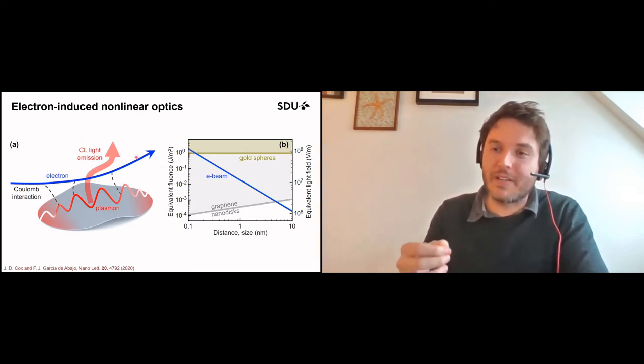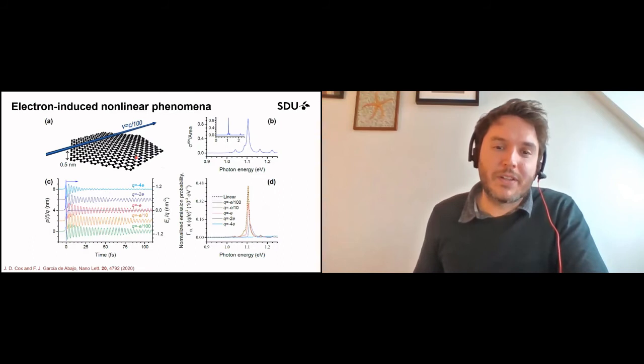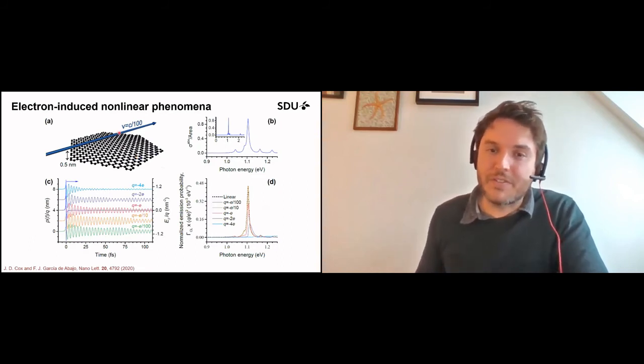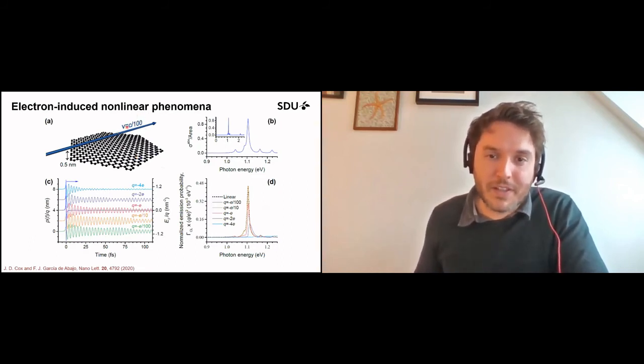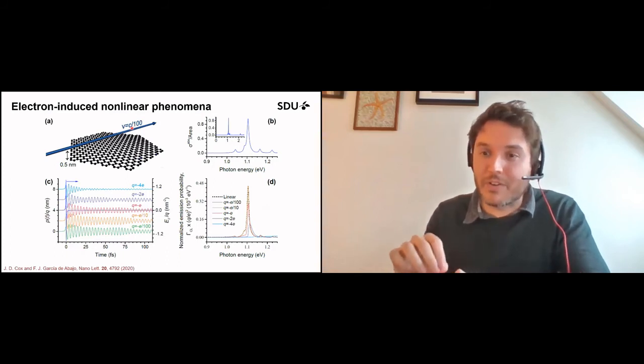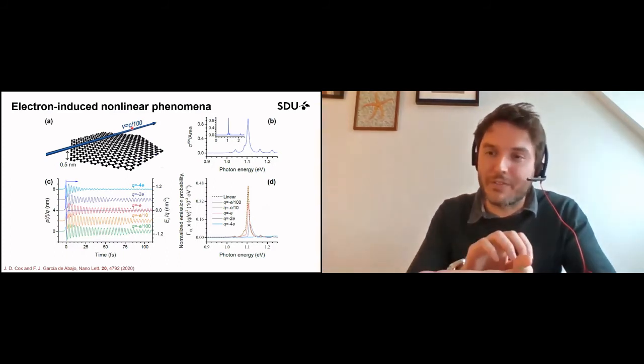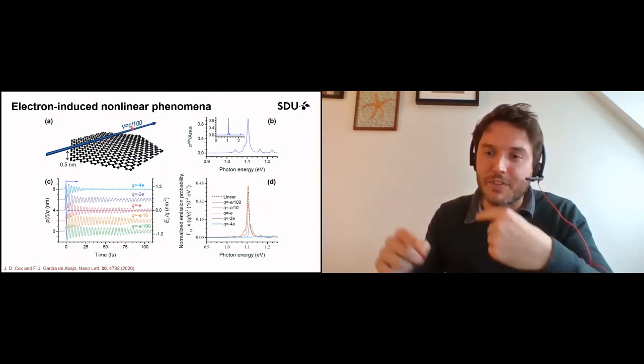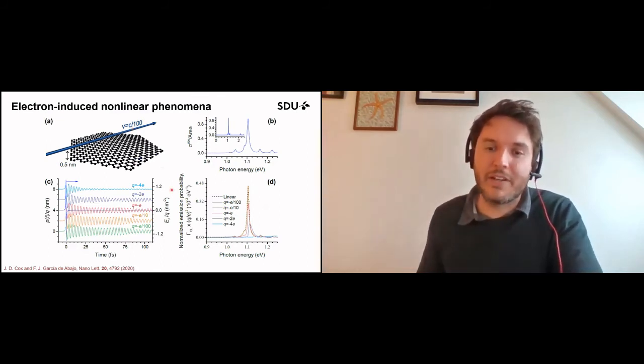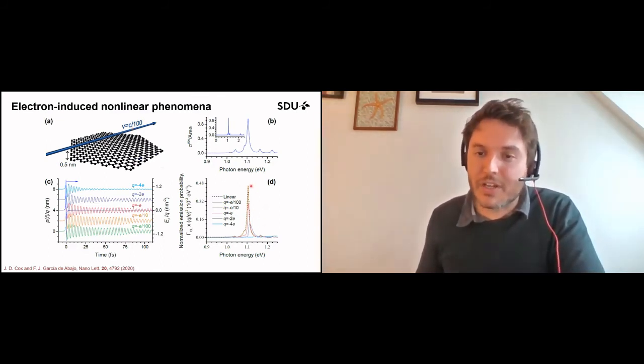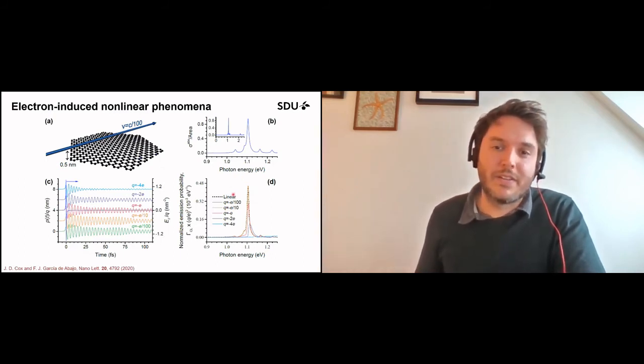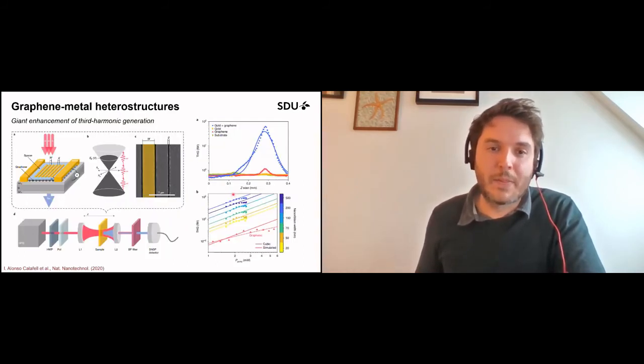It turns out that under the right conditions, you can actually trigger observable changes because of this electron moving very, very slowly. If it's moving very slowly past the island, there's more self-interaction and more optical nonlinearity, and you can effectively quench cathodoluminescence or shift to different frequencies in these graphene islands.